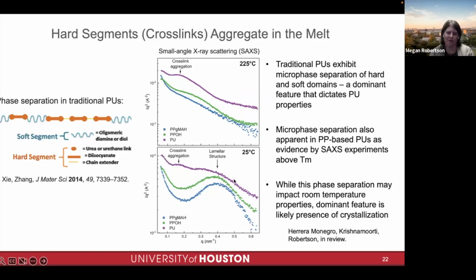Now we're below the melting point, so the polymer can crystallize. By the way, you'll see a lot of plots in this talk. The purple is generally the polyurethane. The green is our hydroxylated polymer that we cured to form the polyurethane. And the blue is the maleic anhydride grafted material that was the starting point for forming the hydroxylated material. But in all three, we see evidence of crystallization. And only in the polyurethane, we see this cross-link aggregation behavior, which again is characteristic of other polyurethanes.